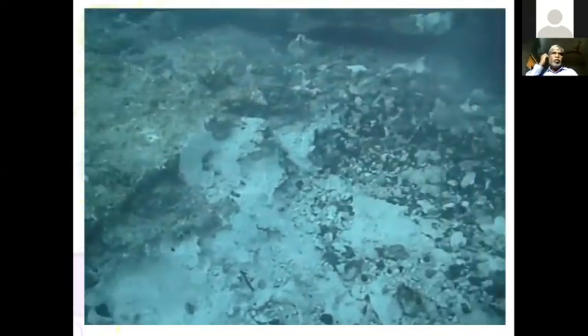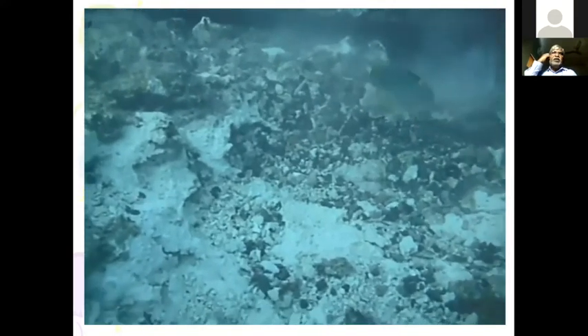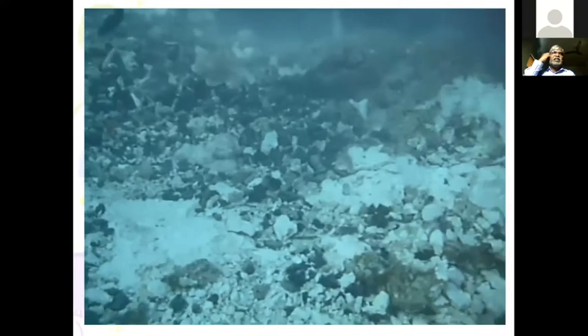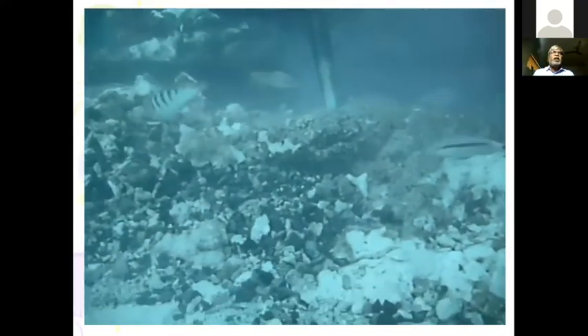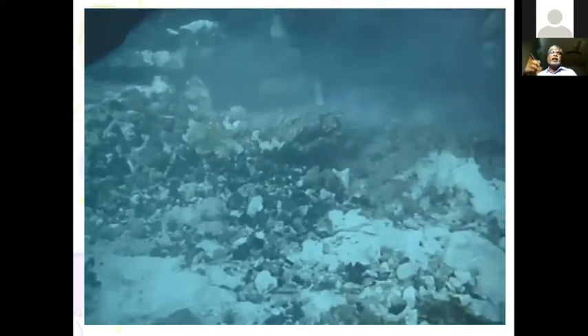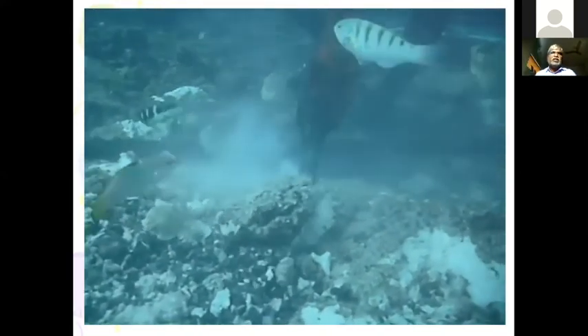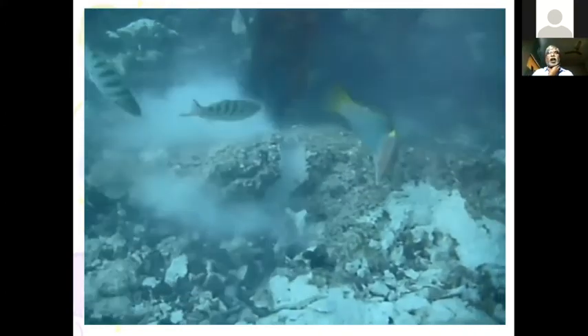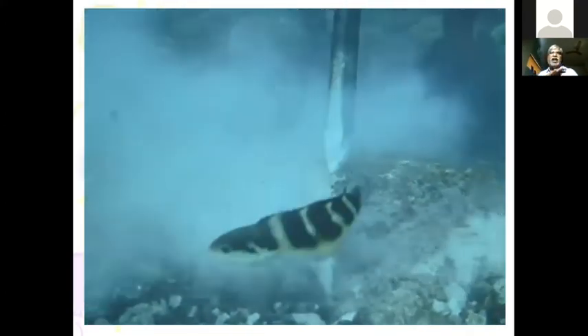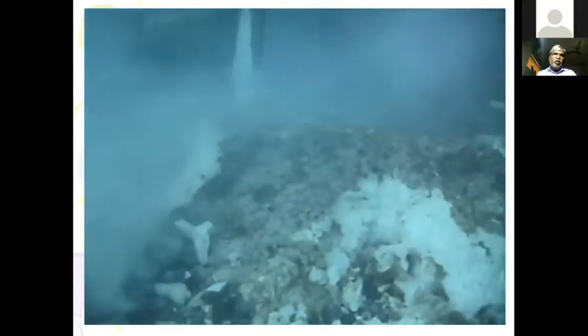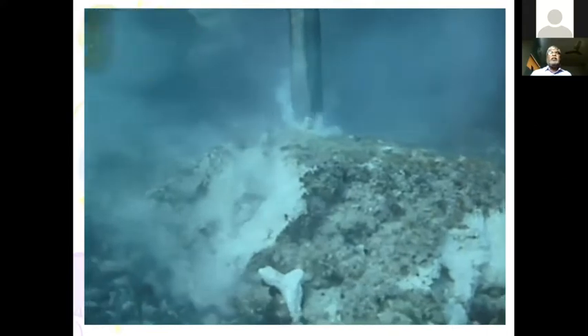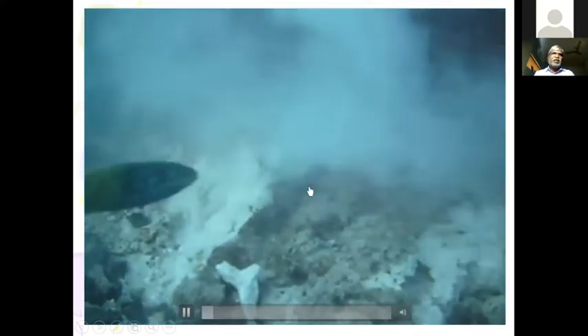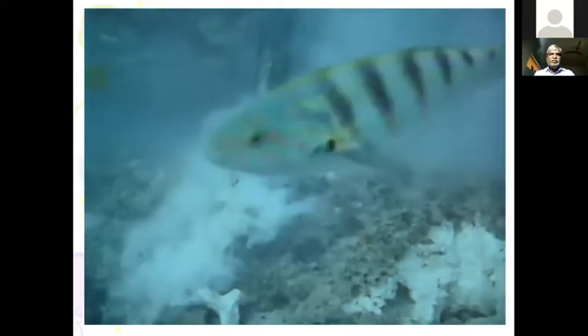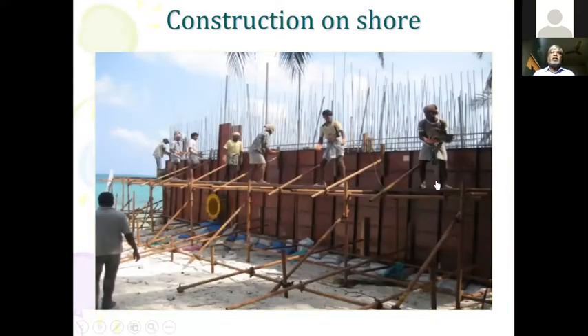We have also proposed to go with a pipe on the raft foundation, so that once the sump, or the floating structure, is anchored into the seabed to a depth of about 12 meters through a 32 millimeter diameter anchor rod used with polyester resin which sets underwater. We also wanted to grout the base of the raft after construction and the seabed with non-shrink underwater grout. For that, chipping was done to the maximum possible extent, so that we don't have any point load coming onto the raft, because it is designed as a UDL. There's nothing to show about it.